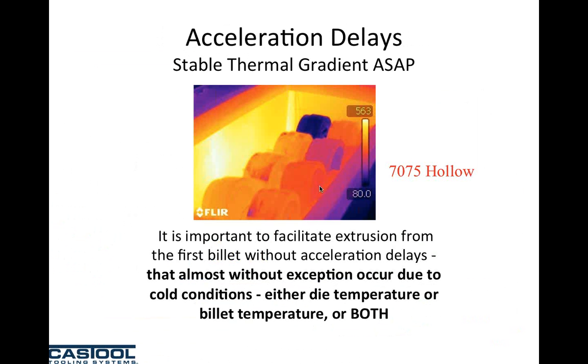And if we go back to a strong die, if you had a weak die, you would break the die. So the die designs that they're using to start the dies with, say, 2 to 4 billets are also strong, slow dies. By no means do they have any chance whatsoever to be a super extruder, because their billets are out of control, their dies are out of control, and their billets are cold, which makes them strong with high flow stress. Their dies are too strong, which increases flow stress, which causes them to use hot billet temperatures and slow ram speeds to get their exit.